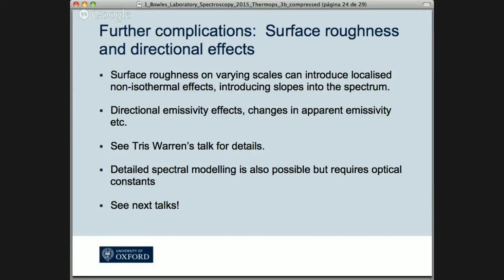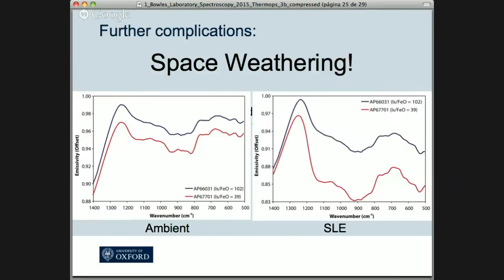Space weathering is something I haven't mentioned, and in fact I haven't heard it mentioned much this week at all, which is interesting. Here's some very provisional data for a couple of different Apollo samples showing the effects. This is Apollo 16, a very immature soil and a more mature soil, showing the effects in the thermal infrared that we see for the Moon. This is extremely new, so we don't have any good interpretation of what's going on here. You can see that although the CF is maintaining its position roughly, there's a little bit of shift. You do also get some changes in the band strengths, which is interesting and needs further investigation.